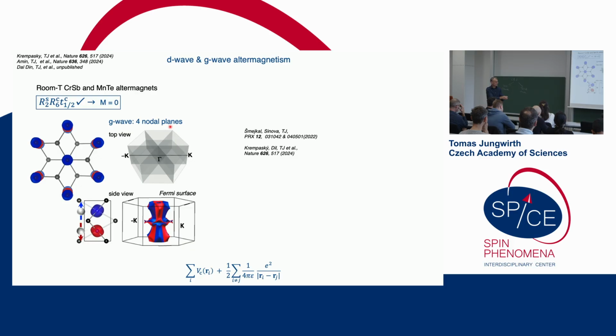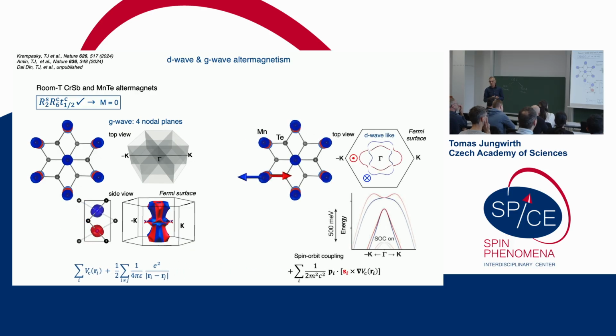And the other means that I want to show now is relativistic spin-orbit coupling, okay? Relativistic spin-orbit coupling lowers the symmetry because spin is now in the Hamiltonian, so you break the spin rotation symmetries already on the level of the Hamiltonian. One particular demonstration, and I believe Libor already mentioned this, is that if I look at this kz equals 0 nodal spin degenerate plane in the non-relativistic electronic structure, when I turn on spin-orbit coupling, I see that there is a spin polarized Fermi surface at the kz equals 0 plane, and it has this D-wave-like symmetry. It has these 2 Fermi surfaces that are anisotropic. And so it has low enough symmetry that you will have spin-dependent conductivity in the bulk. You don't have to chop the crystal.